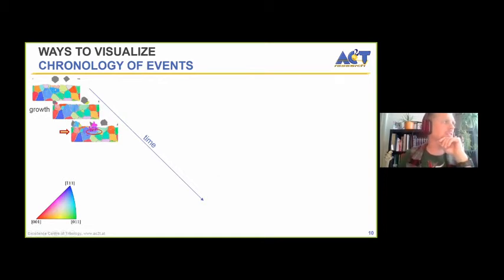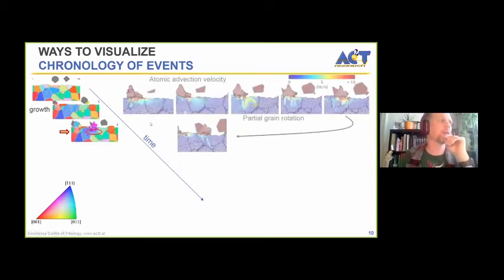So here we're looking at this blue grain, and the pink one here gets abraded to a certain point where the grain boundary moves up towards the surface. The blue grain starts growing, which you see here. And then suddenly there's a rotation and the formation of a low-angle grain boundary. And she was wondering, okay, can you show me a little bit more about how this came about?